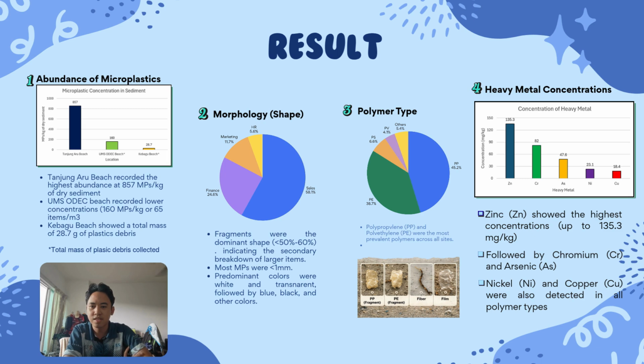Lastly, for heavy metal concentration, zinc showed the highest concentration among the detected metals, followed by chromium and arsenic. Nickel and copper were also detected across different polymer types. These findings are significant because microplastics may act as carriers of toxic substances by absorbing heavy metals from the surrounding environment. As a result, contaminated particles can potentially be ingested by marine organisms and enter the food chain. Overall, these findings demonstrate that microplastic pollution on recreational beaches involves not only the presence of plastic particles but also potential ecological risk due to the association with heavy metal contaminants.